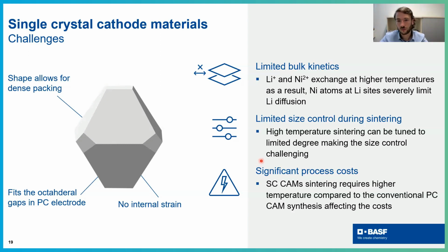And now, if you put all these problems together, especially kinetics, lithium-nickel exchange, and high temperature, you can imagine that by going to high temperatures, you're inducing lithium-nickel site exchange and a lot of defects. So you have to go for sintering, but as a side effect, you're really getting problems with kinetics. And this is what we're trying to optimize, let's say.